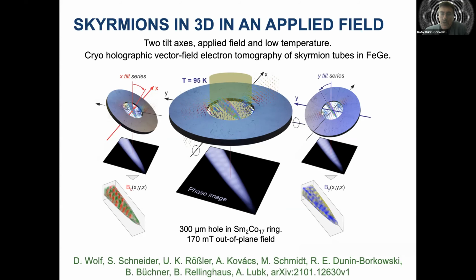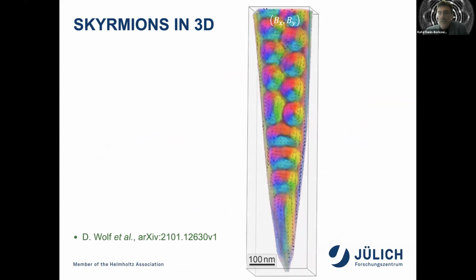And in this way, the 3-dimensional distributions of the 2 in-plane components of the magnetic field can be reconstructed separately, and then the criterion from Maxwell's equations that the divergence of B has to equal 0 can be used to reconstruct the 3rd component of B from the first 2 3-dimensional reconstructions. And this works very nicely. Here is a 3-dimensional representation of the in-plane components of B reconstructed in 3 dimensions.